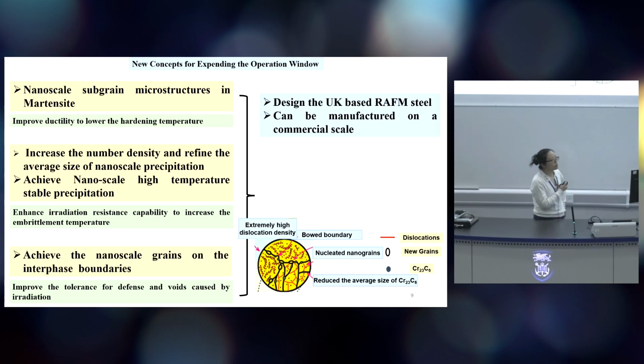In my concept of steel design, I will produce nanoscale subcell structures in martensite. This structure will improve the ductility, which will benefit the low temperature hardening. I will also keep the same concept of producing high temperature stable precipitates, but I will maximize the number density and refine the precipitate size, so we can maximize the trapping effect on the defects and voids induced by the irradiation.